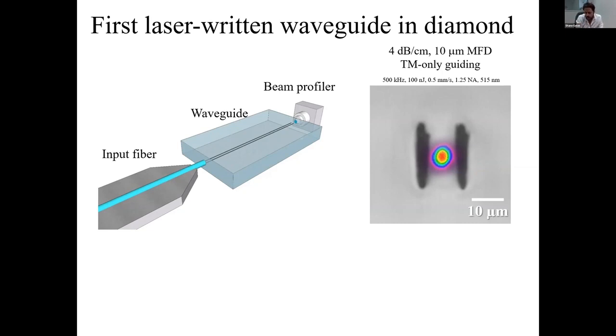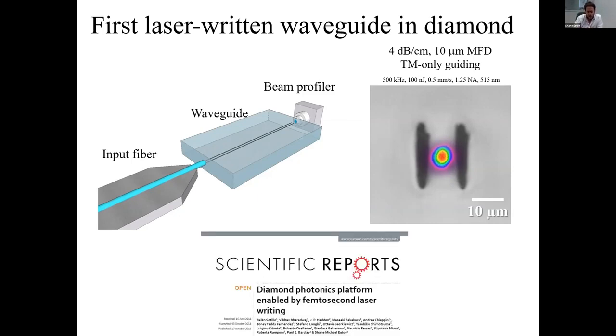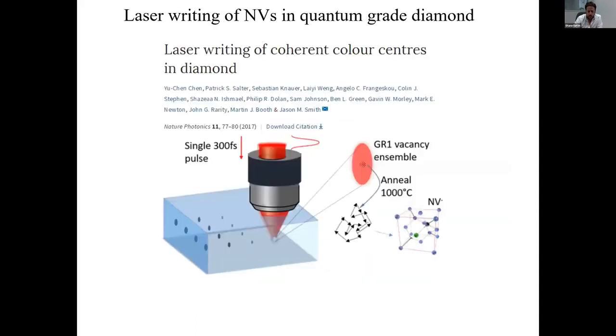But regardless, we found nice single mode guiding. Losses were reasonably low, around 4 dB per centimeter in the visible. One other thing to point out is that we had only TM guiding in the case of this waveguide. And here shows the various laser processing parameters, which may be of interest to some people. This was published back, I believe, in 2016 in Nature Scientific Reports.